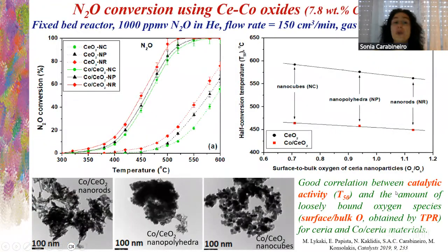So we use, remember, the cerium oxide nanorods, nanopolyhedra, and nanocubes. We use them with cobalt, okay? With cobalt, we tested for N2O conversion. So we saw here similar results to CO oxidation, and again, a good correlation between the catalytic activity and the amount of surface oxygen species. So it's here both for the samples with and without cobalt. Okay.